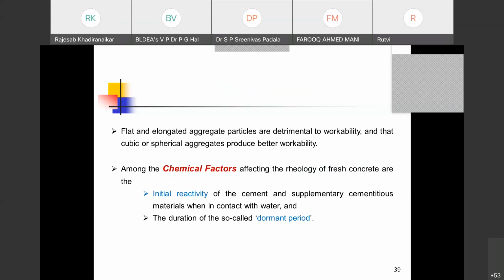The flat and elongated aggregate particles are detrimental. Of course, we are not using them. As I said, the cubical shape is better rather than elongated or flaky, which are detrimental to workability and even to strength, and from the transition zone point of view also, they are not good. So we have to go for cubical or spherical shaped aggregate, and they produce better workability. Among the chemical factors affecting the rheology of concrete are the initial reactivity of the cement and supplementary cementitious materials when they come in contact with water, and the duration of the so-called dormant period. So this is also important.